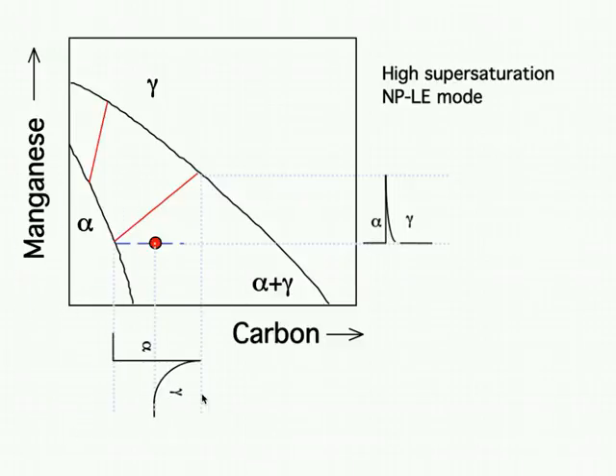So this is now going to be a fast reaction because we are partitioning very little manganese, and manganese is usually the slow diffuser. But we are maintaining local equilibrium at the interface. So there are these two ways, the negligible partitioning local equilibrium and the partitioning local equilibrium modes for ferrite growth.